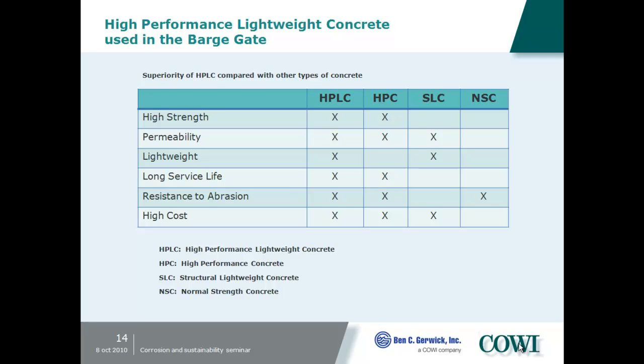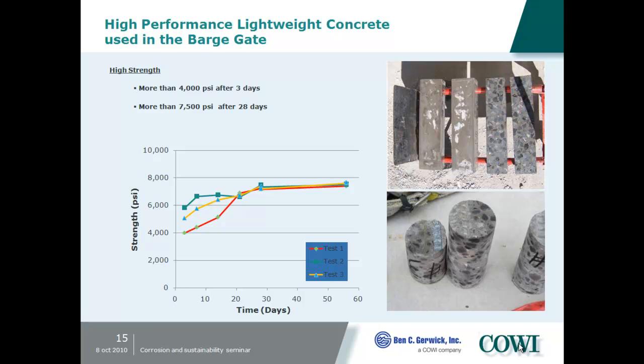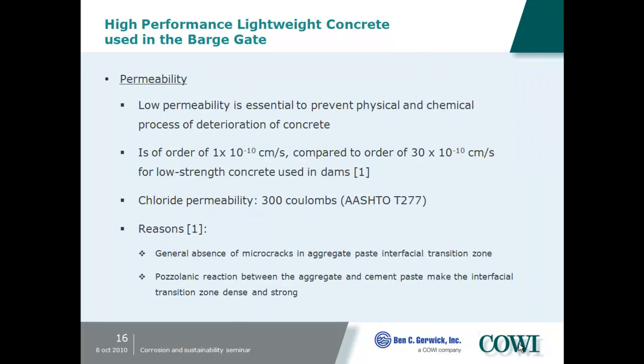But fortunately it gave us also better service life by decreasing permeability, and we had very good strengths on it, so we have this issue about service life that Eric was talking about. So again here, we had this 4,000 psi after 3 days, more than 7,500 psi. That's often good just for standard weight concrete, and here we're getting it with semi-lightweight. I should point out that here we used standard weight sand. It was just the coarse aggregate that was lightweight, but you can see here's the strength gain with time for different breaks.